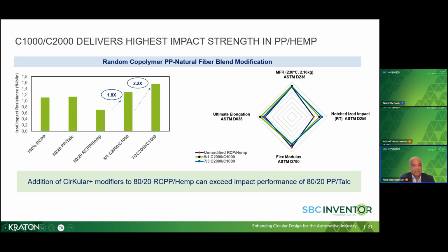So what we show in this example is how the CirKular+ modifiers work in systems containing a blend of polypropylene and hemp. If you look at the chart on the left-hand side, when you add 20% hemp to recycled polypropylene, the notched Izod drops off at the onset by almost 40%. In comparison, when you add 20% talc, we are almost able to maintain the notched Izod.